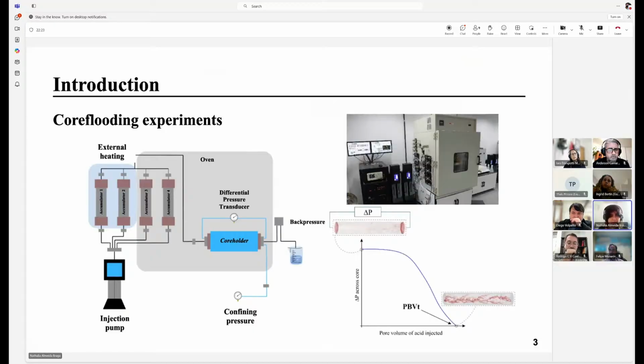In the laboratory, what we have here in LC in Salinopolis, we can study the efficiency of this process with core flooding equipment. A core flooding is an equipment to simulate reservoir conditions at a plug scale, so the scale of a carbonate sample around 6 inches in length, 1.5 inches in diameter. This sample is pressurized inside the core holder, and fluids are injected with the help of an injection pump. So the fluids go from the accumulators to the core sample inside the core holder. And we can heat the system to simulate reservoir temperature too.